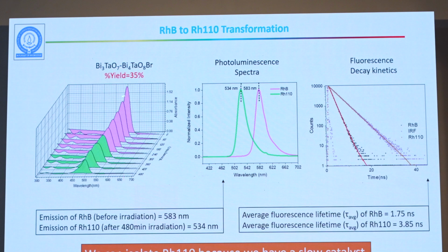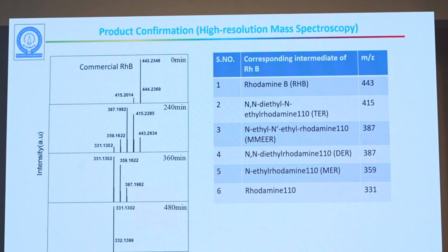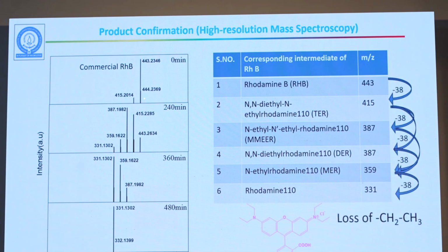These are something about the two dyes. We get about 35%, and we confirm that this is a completely pure dye. When you buy from market, even the purest dye is only about 99%. So this is nearly 100% pure dye. We looked at the mechanism. When you looked at the mechanism, what you see is that rhodamine B, this is a mass spectra, and you see there's a series of peaks. Now, when you see it, the molecule slowly loses its mass in a very typical fashion.